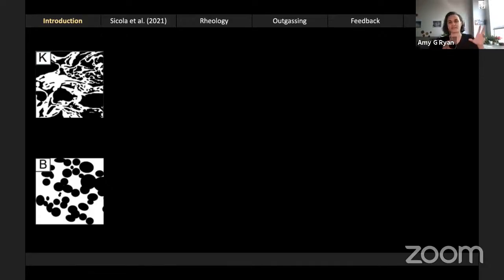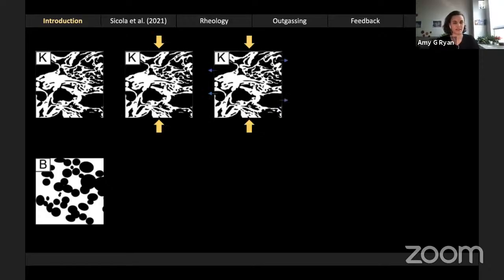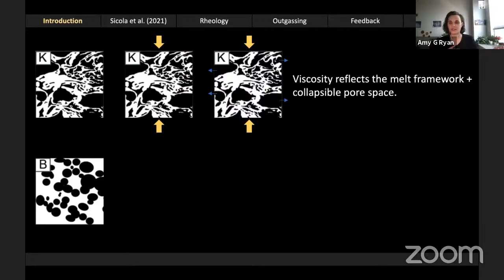To bring in the rheology side, because that's a majority of what I've worked on, now let's imagine compressing each of these materials. On the top, if I were to compress the schematic here, and let's just call it uniaxial compression, so the sides are unconstrained, you can imagine that as I compress, the pore fluid that fills that intergranular space will be evacuated or purged out the sides as a result of compression. So if I'm collecting mechanical data during compression and I'm calculating from that a viscosity, that viscosity is telling me something about the melt framework, but it's also telling me something about how easy it is to collapse the pore spaces.